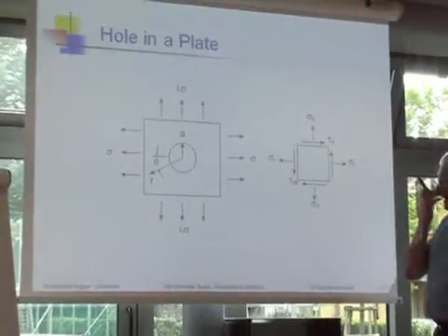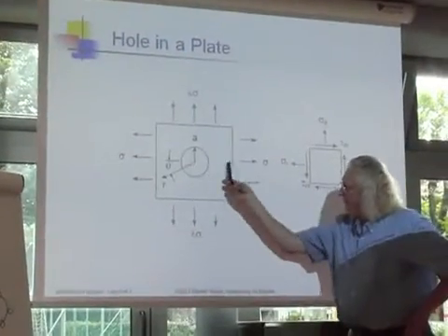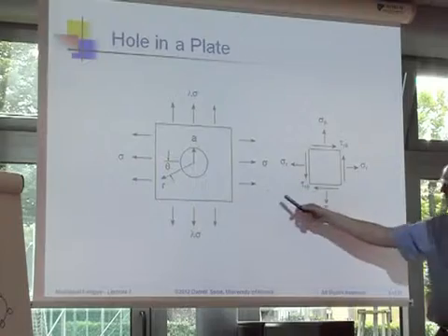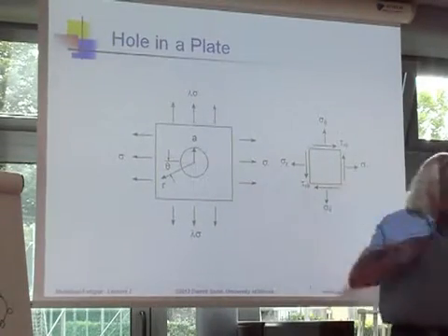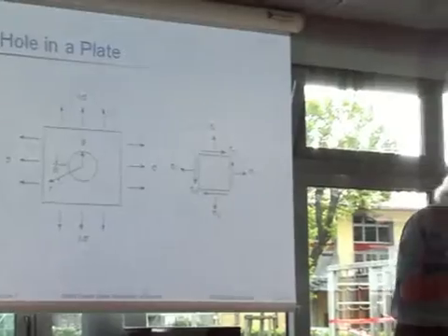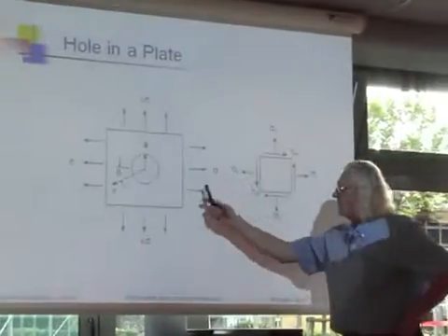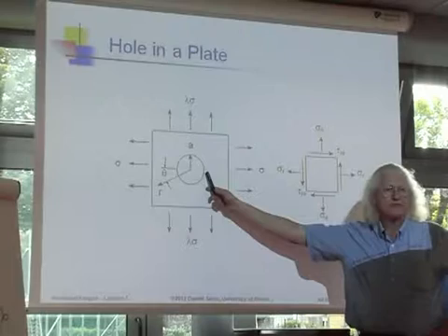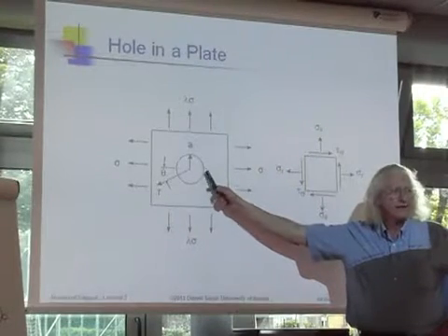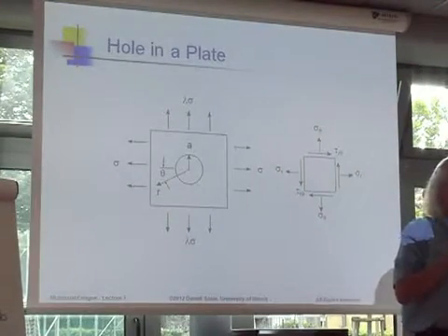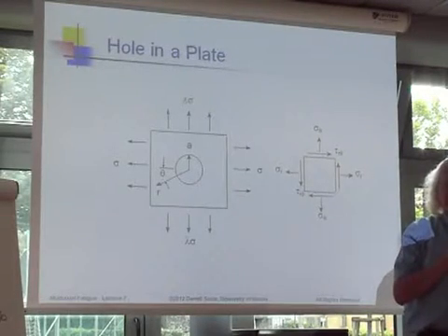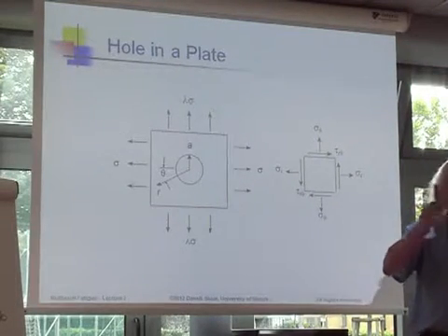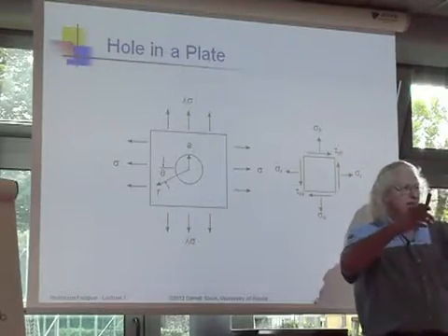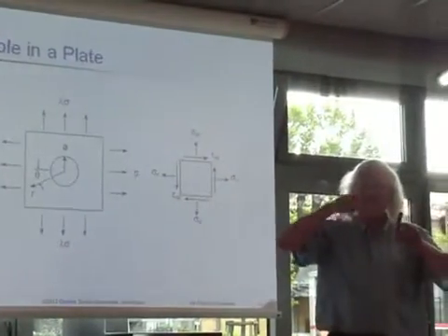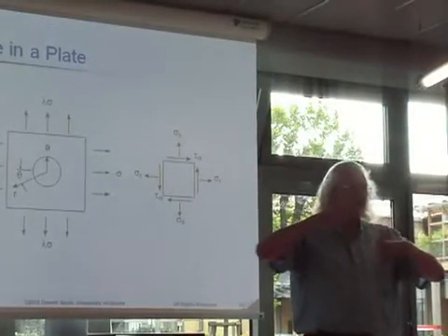And then, of course, I can have a radial stress. That's a stress which goes this way. And then I can also have a shear stress at the edge of the hole. And what you find out is, of course, that the radial stress must be 0 at the edge of the hole because it's a free surface. And the shear stress must be 0 at the edge of the hole because it's a free surface. So what you find is no matter how complicated I make the loading for a plate with a hole in it, stresses around the edge of the hole where the cracks circulate are always uniaxial. So it's always a uniaxial fatigue problem.